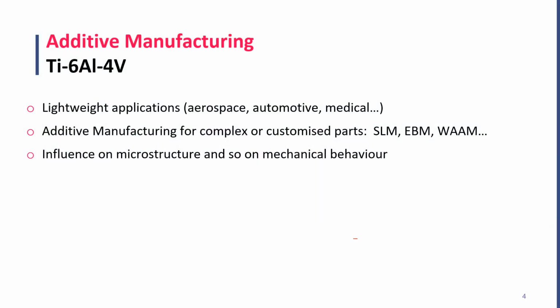The choice of titanium-64 is based on its very good mechanical properties, similar or even better than, for example, high-strength steels, but with a lower density, so this is perfect for lightweight applications. The use of additive manufacturing has been very common during this last decade, due to the need of complex or customized geometries. However, as we know in our field of structural integrity, these methods strongly influence microstructure, and so the mechanical behavior.